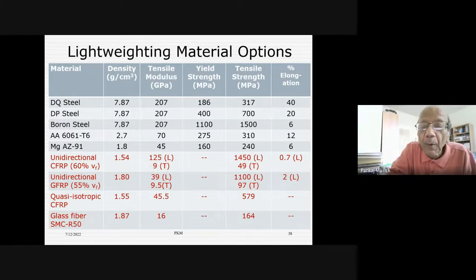Then look into something called boron steel. Boron steel has a yield strength of 1100 megapascal and a tensile strength of 1500 megapascal. So steel companies are producing these high strength steels. The higher the strength, the lower would be the thickness that you require to design a part, while the strengths are increasing, the density and modulus do not change. If you go to aluminum 6061 T6, it has a density of 2.7, and that's why there is so much interest in replacing steel with aluminum. Modulus is also much lower, and strengths are also lower.